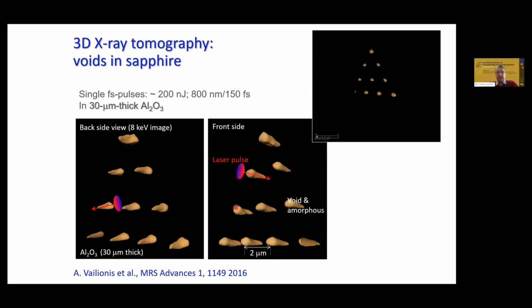In the very first experiments, we were using sapphire, which is the hardest oxide in nature. We had a very thin film of sapphire, which is required for tomography measurements. If you write a pattern of single-shot illumination and look at different angles, you can see that all those structures of modified volume are enclosed. It's slightly elongated because of spherical aberration, but it's very well localized.